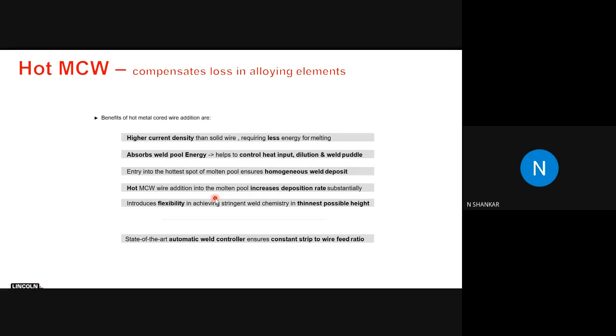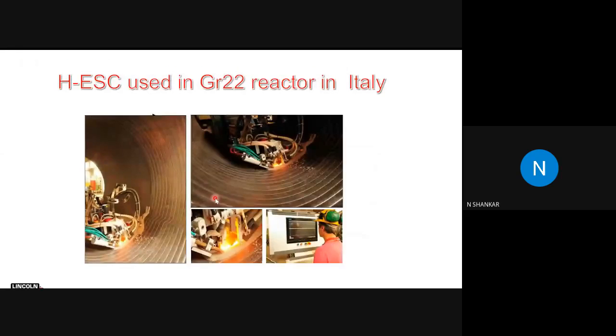The metal core is fed into the hottest part of the strip, and it does a homogeneous weld deposit. Hot metal core wire addition to the molten metal increases deposition rate substantially. It also introduces flexibility in achieving stringent weld chemistry in the thinnest possible height by adding additive material, whatever alloying element you want, you can use in the metal core wire. So that is one successful application that Lincoln has done, the hybrid electroslag strip cladding application.